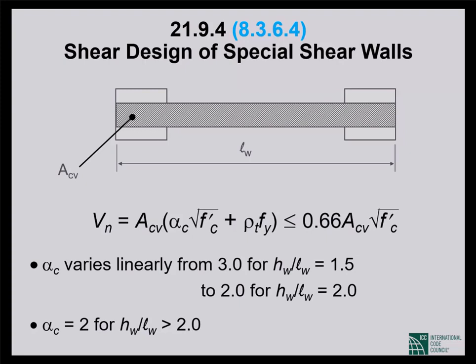But years ago, there were tests at Portland Cement Association of low-rise shear walls that showed if you have height to length ratio below 1.5, your shear wall can do better. That the concrete in your shear wall can carry more shear than 2 square root of f sub c prime. So since then, we have said that for height to length ratio of 1.5 or less, concrete is good for 3 square root of f sub c prime. For height to length ratio of 2 or more, concrete is down to 2 square root of f sub c prime. For height to length ratios between 1.5 and 2, we interpolate between 3 square root of f sub c prime and 2 square root of f sub c prime. Okay, 3 and 2 in our units, 2 is 0.17, 3 would be 0.25 or something like that. Okay, I should have had the metric equivalent here, but I don't.